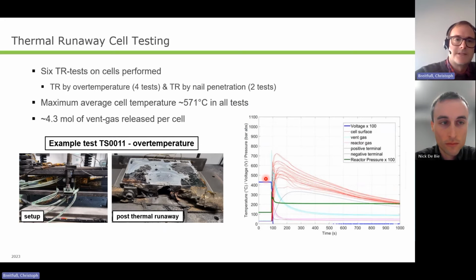Now we come to thermal runaway testing of the cell. We did all in all 6 tests with the cell. We used different thermal runaway initiation, over temperature by heat bed at 4 tests, and nail penetration with 2 tests. There was no mean difference in the test results, so all tests are very similar. The maximum average cell temperature was 570 degrees over all tests, and we had on average 4.3 mole of vent gas released from this cell.